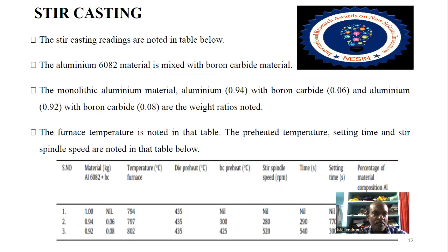Stir casting. This is the initial method. The stir casting readings are noted in the table below. The monolithic aluminum material, aluminum with 0.94 and boron carbide 0.06 ratio, and aluminum with 0.92 and boron carbide with 0.08 are the various weight ratios noted. This aluminum 6082 material is mixed with boron carbide. Various fractions of boron carbide are mixed.